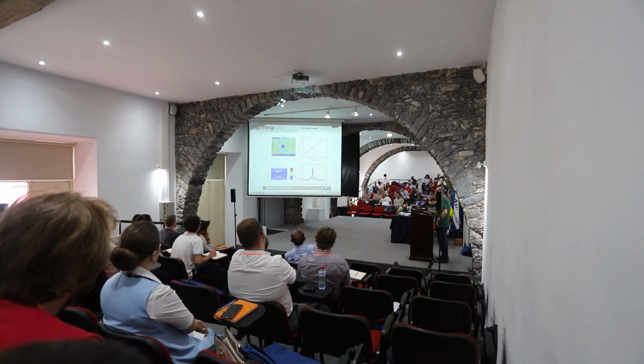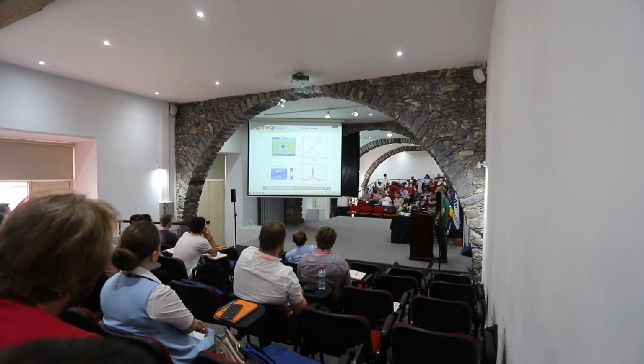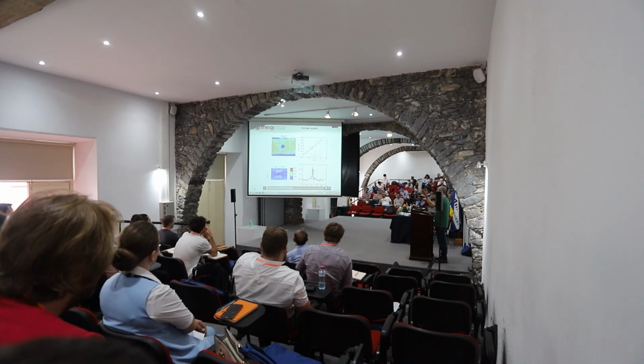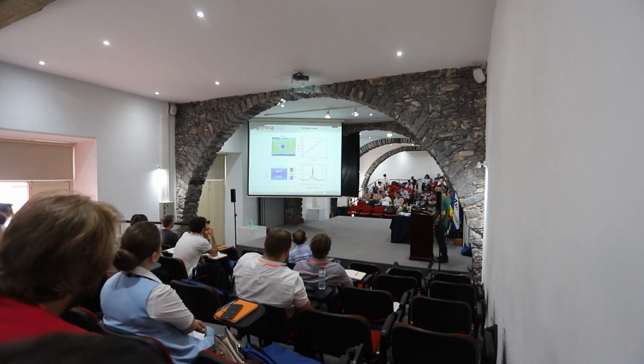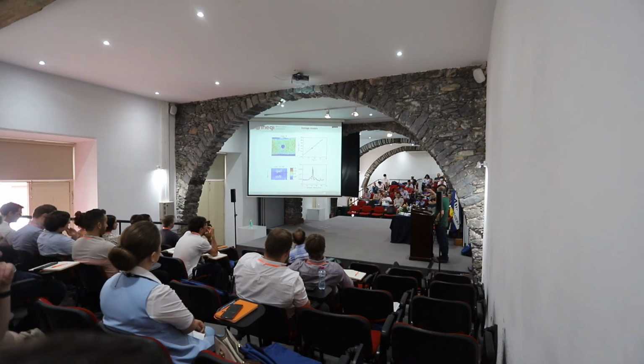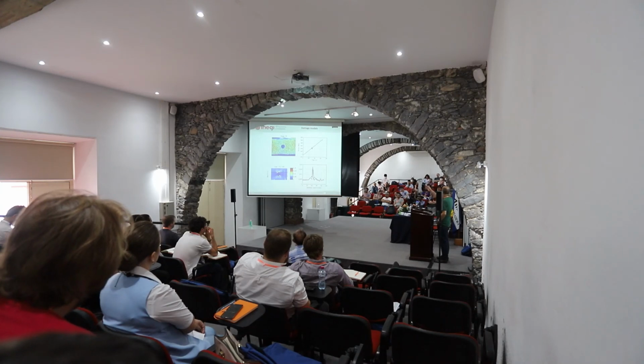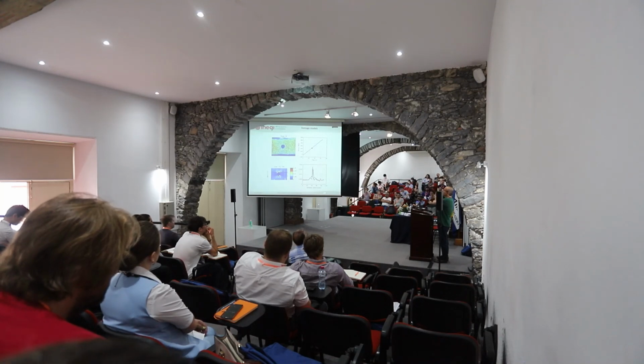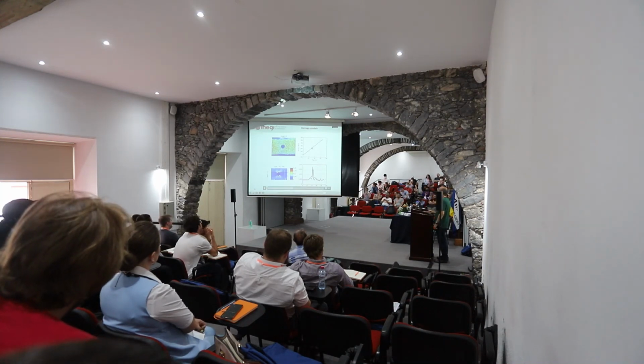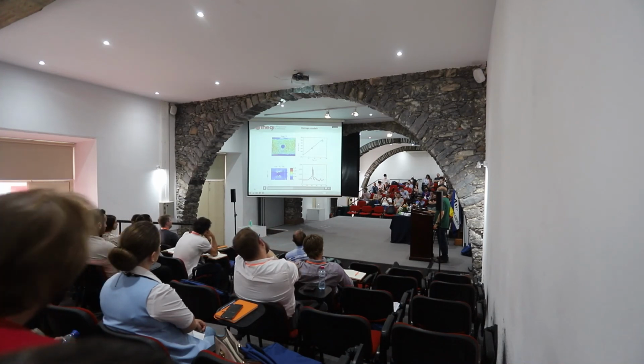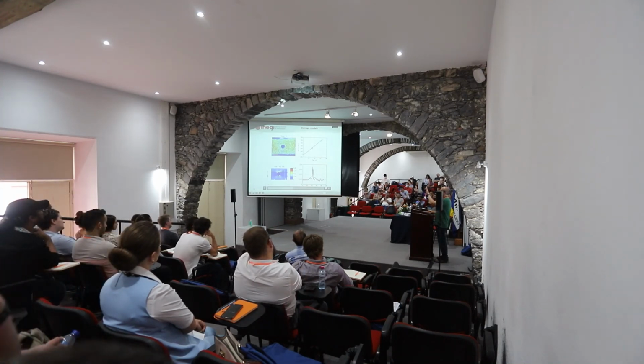You get these peaks of strain that in reality are a discontinuity because it's a crack. It's a discontinuity in the displacement field, so it should be a Dirac function there. It's not because this is smoothed out due to digital image correlation. You get these two cracks. So the failure criteria will give you this. If you just use a failure criteria, you know your specimen has cracked. But then you cannot say this is the ultimate failure load of my specimen, because this is just over 200 megapascal and the specimen will fail at over 500 megapascal. So you need to identify the onset of damage, but then you need to propagate damage.